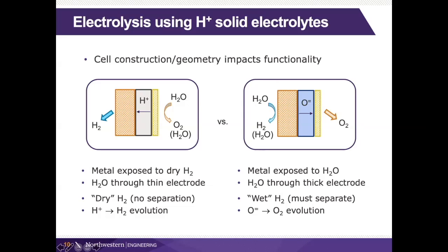And it's actually exposed to a lot of steam because we have to have a lot of steam here in order to not have mass diffusion losses to get this sort of bulky molecule all the way through this thick electrode. In the case on the proton conducting side, hydrogen can easily make its way out here. And this is a thin electrode. So the water and the oxygen, which are slightly bigger molecules, can make their way through this thin air electrode. And then in this case here, you'd have to separate the fuel afterwards from the water.